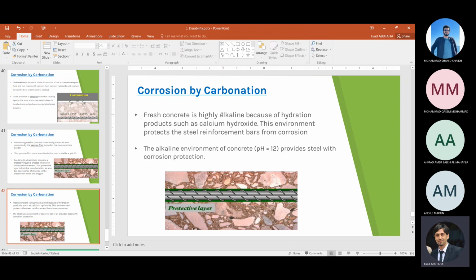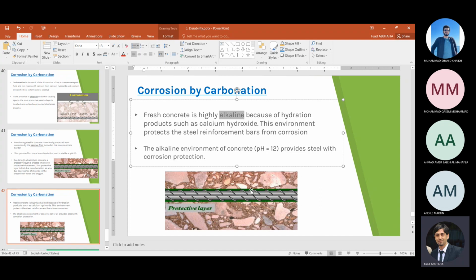So fresh concrete is highly alkaline. High alkaline means that it has a high pH value, because of the hydration products such as calcium hydroxide. This environment protects the steel reinforcement from corrosion. So the high alkaline environment is a good environment for the steel to be protected. But if the alkalinity is reduced, which is reflected by the pH value, when the pH value is reduced lower than 12, lower than 10, it can reach down to 7, 5. So the lower it is, the lower the quality of the passive film, and the steel bars will no longer be protected from corrosion. So corrosion will start.